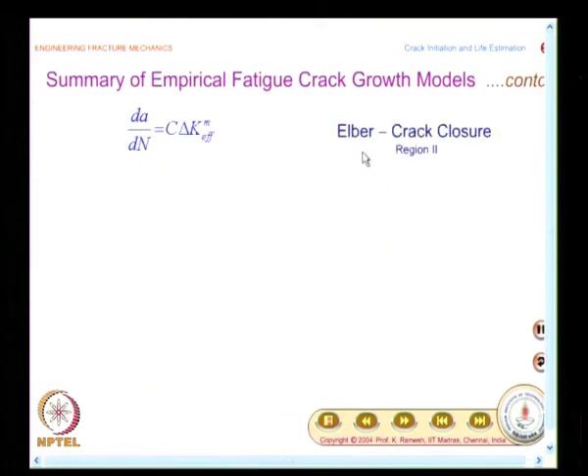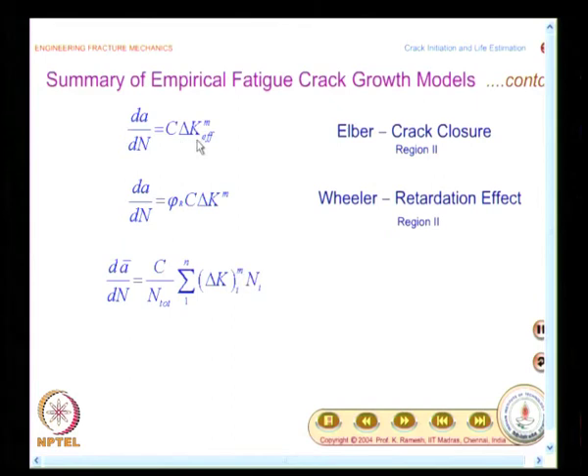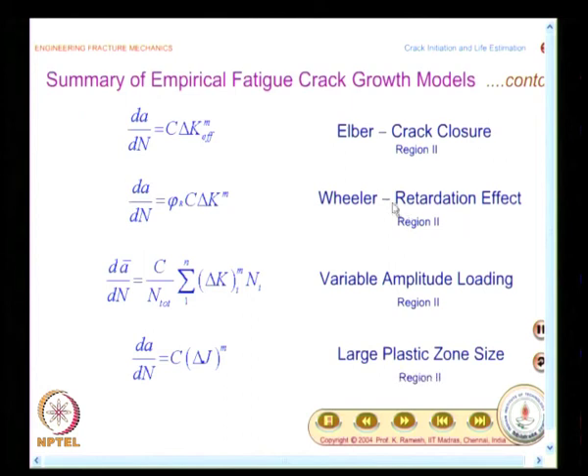We have the crack closure introduced by Elber. You have dA/dN equal to C delta K effective whole power m. And when you have a retardation effect introduced by Wheeler, you have dA/dN equal to phi r C delta K power m, where phi r is the retardation parameter. Then if you have a variable amplitude loading, you can calculate average crack growth rate, dA bar divided by dN, equal to C by n total, sigma 1 to n, delta K i whole power m, multiplied by n i.